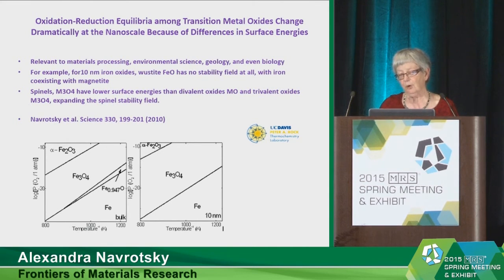And indeed, I believe nobody succeeded in making FeO nanoparticles. They always come out magnetite, because in fact the wüstite field would start existing only above about 1,000 Kelvin from the calculations, at which point that temperature is high enough to dehydrate and coarsen the particles. So basically the nanoparticles simply cannot be made.